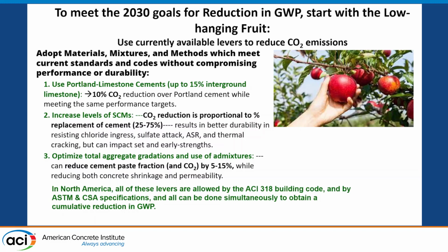And optimizing aggregates, I mentioned, if you just have a fine aggregate and a coarse aggregate, you're not optimizing your gradation. Most ready-mix plants or batch plants in North America use a fine aggregate and a coarse aggregate. The pavers often have an intermediate aggregate, which allows them to reduce their paste content, which is required for pavements. They don't get cracking and volume change, or reduces it. And in Europe and a lot of Asia, in the newer plants, they're using up to 6 different aggregate sizes and combining them to get optimized gradation, which could reduce the paste content, which will not only make more sustainable